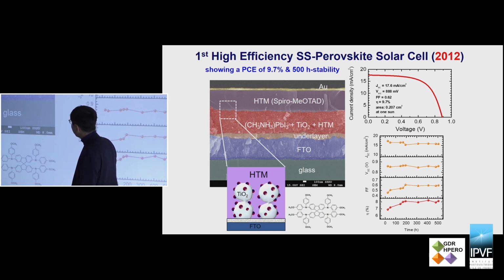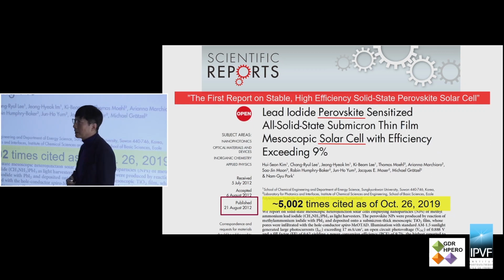At that time we attained a dot morphology, the perovskite sitting on the titanium oxide surface, and the sensitized titanium oxide is fully wrapped by the hole conducting material. The hole conducting material, the spiro compound, is of a slightly hydrophobic nature, so we can guarantee some long-term stability even without encapsulation from this specific structure. So we published 500-hour stability and 9.7% efficiency.